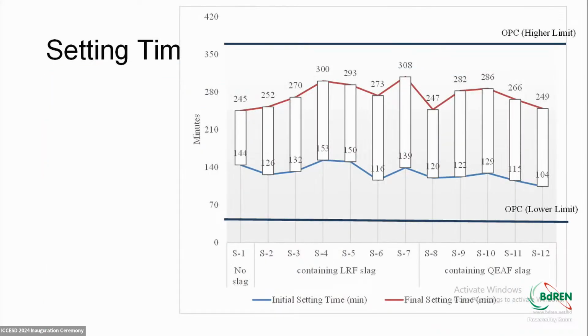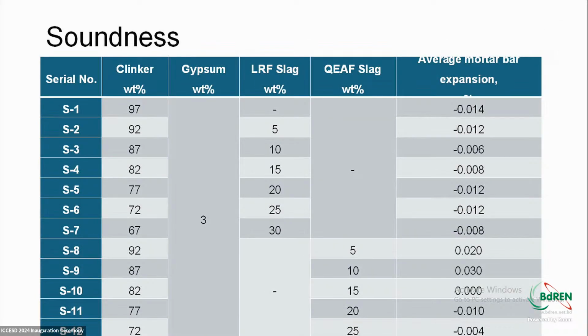Setting time, we measured setting time. It was within the limits, even OPC, ordinary Portland cement limits - the setting time was within the limits. Soundness was also within the limit, but if we increased the QEAF slag more than 25%, then it becomes a problem - expansive properties are then observed.